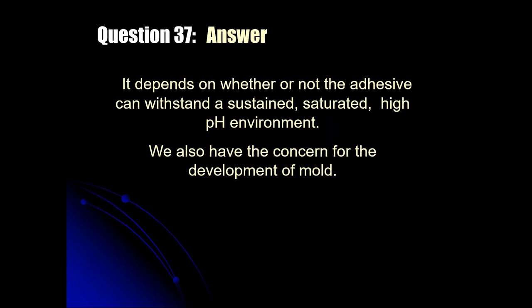It really depends on can that adhesive withstand. Moisture is one thing. A saturated, high pH environment that attacks adhesive can be another. Can it withstand a prolonged or sustained saturated high pH environment? Then also, if we're allowing that amount of moisture to come up and be directly underneath our flooring system, are we at risk for mold?